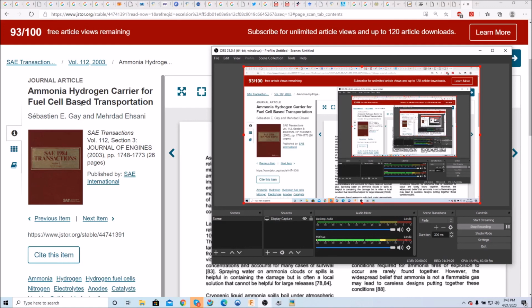For storage density, it's just beautiful. As for gravimetric energy density, weight, kilowatt-hours per kilogram, it's very competitive. From what I gather, it's the highest non-carbon containing fuel. So significantly higher than batteries, an order of magnitude higher than batteries, and twice that of 700 bar hydrogen. And the thing to be noted with hydrogen is that gravimetric storage density doesn't increase much with pressure. So 700 bar is about 5.6%, 300 bar is about 5%. So it's all around the same. It's very poor.